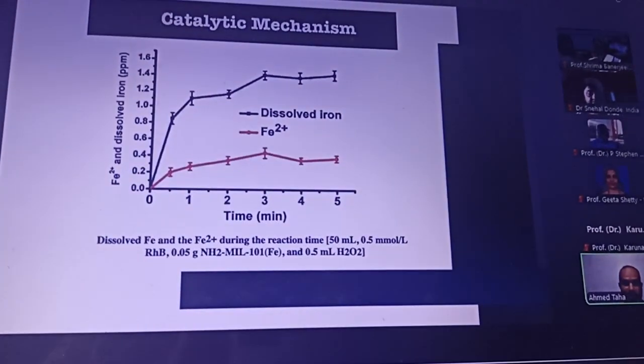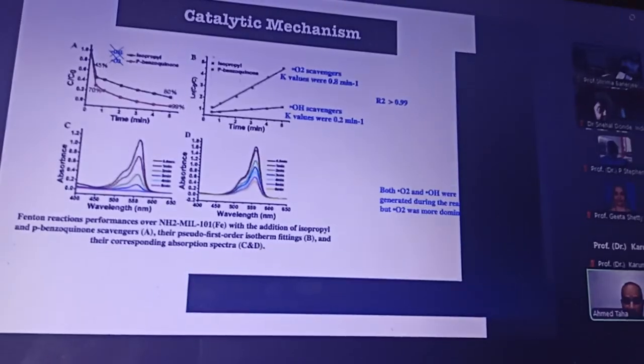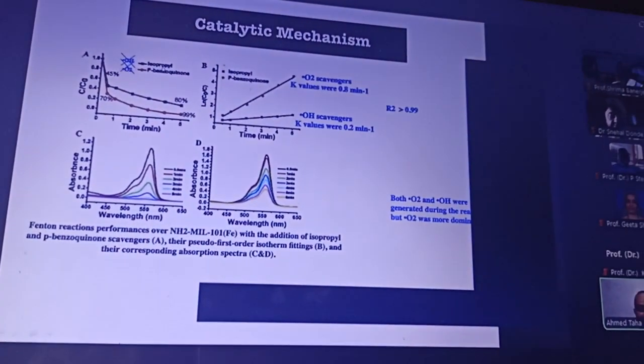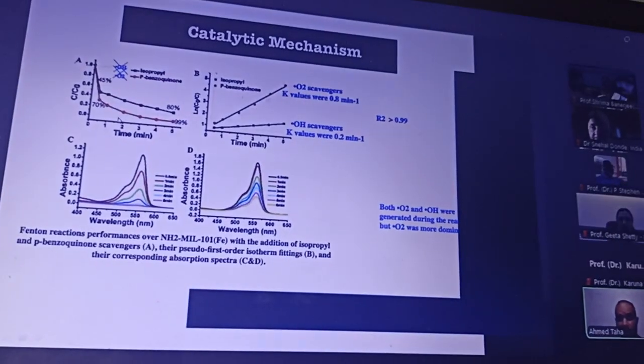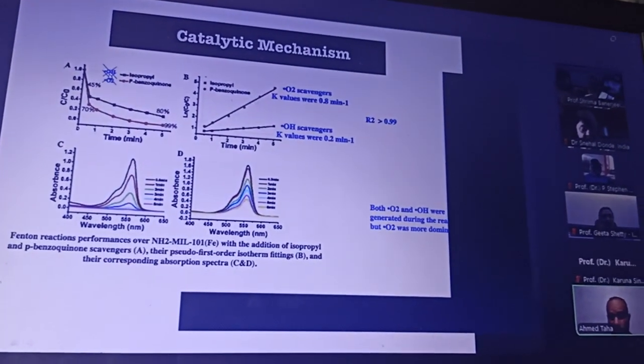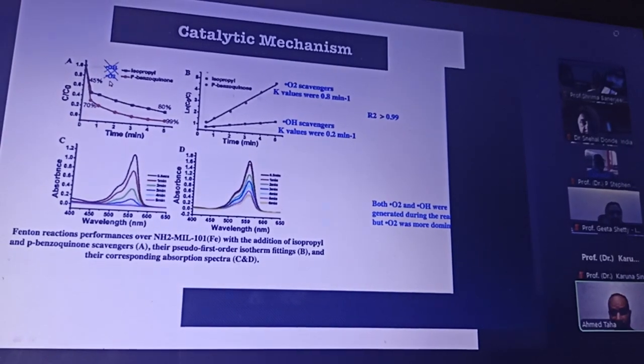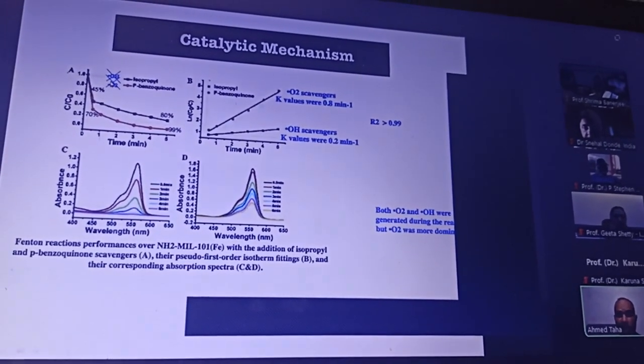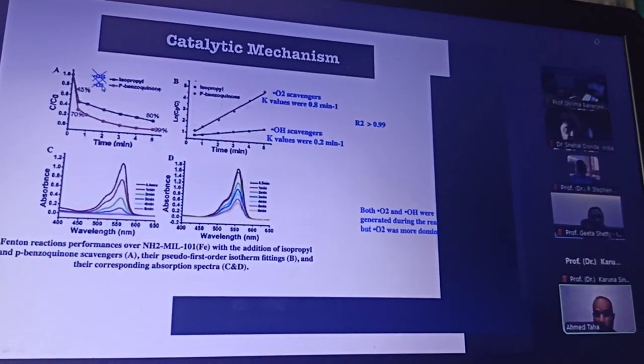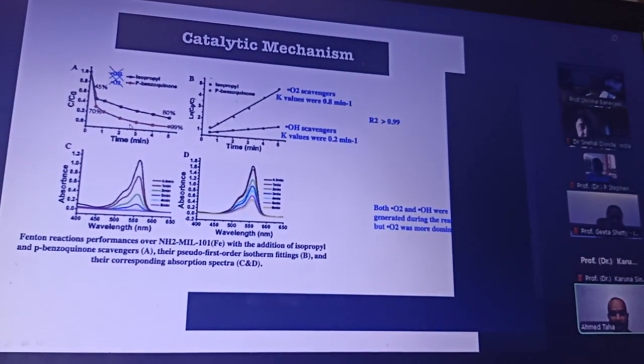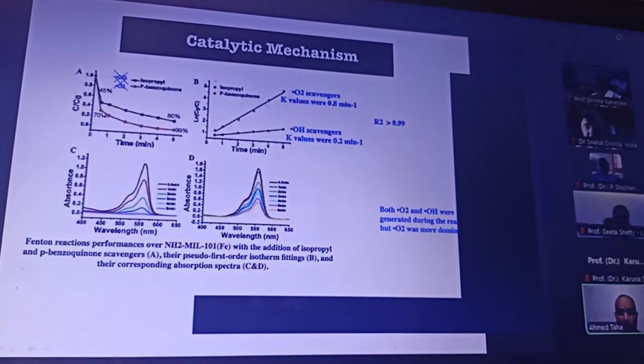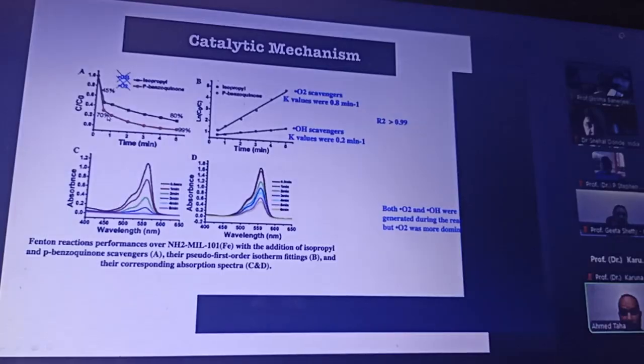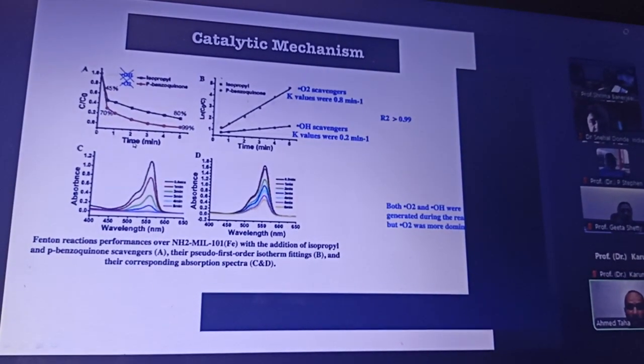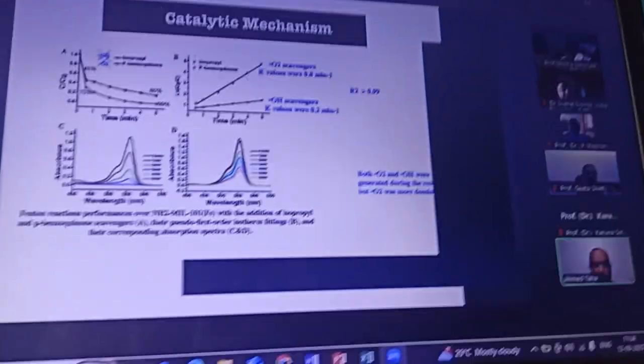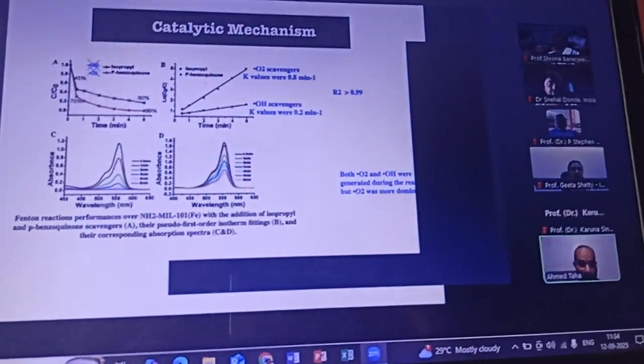Okay, very good. So we also looked at the scavenging of radicals to study the mechanism. We added 2 different materials, isopropanol and benzoquinone, in different experiments. Isopropanol stops the OH radical from the reaction, and the performance is still good. The other chemical we added stops the oxygen radical from the reaction, and the reaction can still work fine. So we can confirm that both the OH radical and the oxygen radical are working together in degrading the organics, but more with the oxygen radicals.